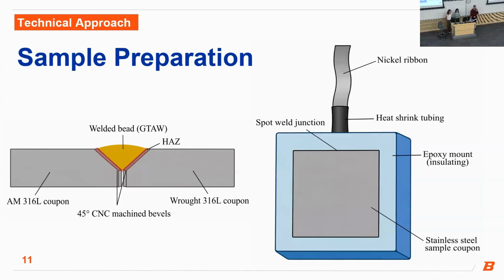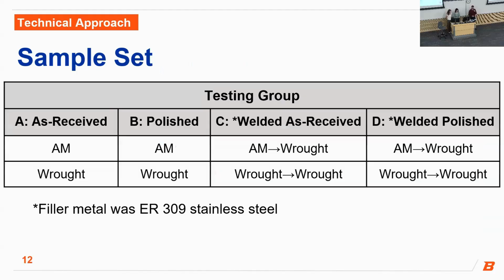The diagram on the left shows the orientation of our welded samples, and the bottom side was our exposed surface side. We had two main sample groups, single samples which were not welded, and welded samples which included 3D printed welded to wrought and wrought welded to wrought. TIG welding with ER309 stainless steel as the filler metal was how they were welded. Each group consisted of samples in the as received or polished condition. Polished samples were polished between 60 to 800 grit to create a smoother surface. Two of the 3D to wrought samples, one as received and the other polished, had a 100 nanometer thick aluminum oxide coating deposited on them by ALD.